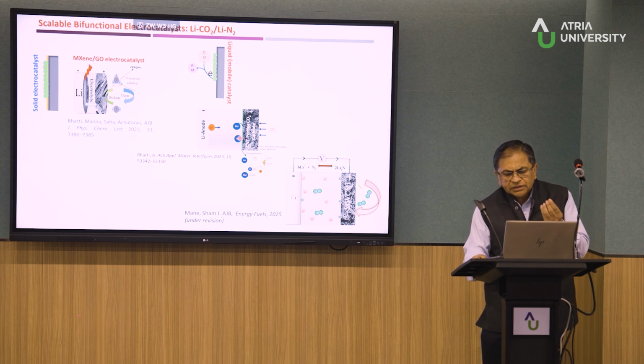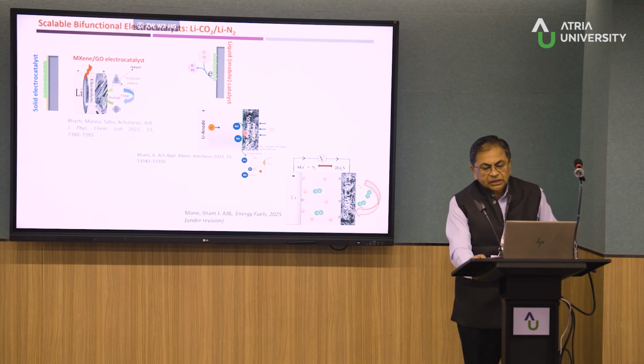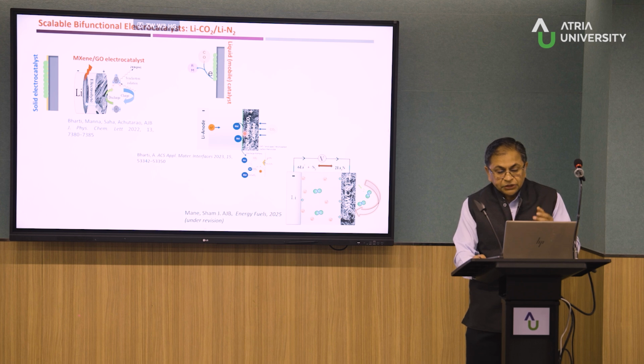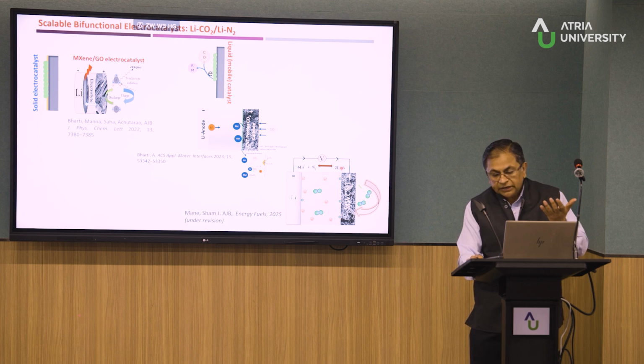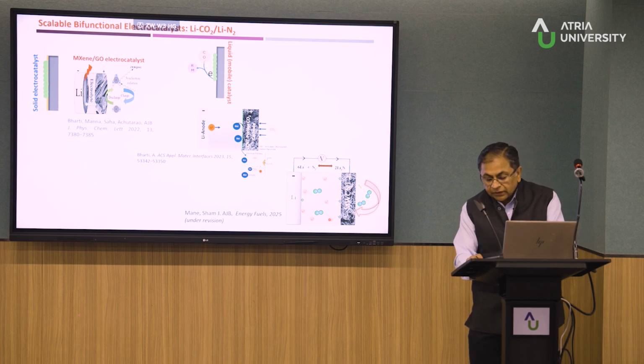So we again looked here at a solid-state electrocatalyst, okay, in the form of MXenes, and then we used a very simple chemical compound like cupric chloride as a redox mediator, which gives very efficient batteries in CO2. And the important thing, again as I said, is that this is an example of carbon capture. You do pretty much the same thing. And then here in nitrogen, you make lithium nitride reversibly. And you can also get a reversible battery.